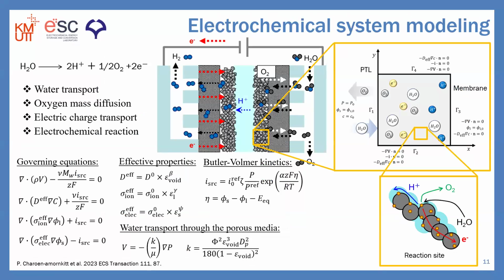When we address the optimization of the electrode structure of the water electrolyzer, we have to develop the model. And in this case, it will be an electrode operating under the isothermal and steady state condition. The porous electrode considered is composed of 3 constituents: carbon support catalyst, electrolyte, and void. Water enters the electrode from the inlet boundary where it is converted into oxygen and proton at the triple phase boundary, and the pores are responsible for transporting water to the reaction site and oxygen out of the reaction site, while the electrolyte facilitates the transport of ionic charge, and the carbon support catalyst enables the transport of the electric charge and decreases the activation energy barrier.